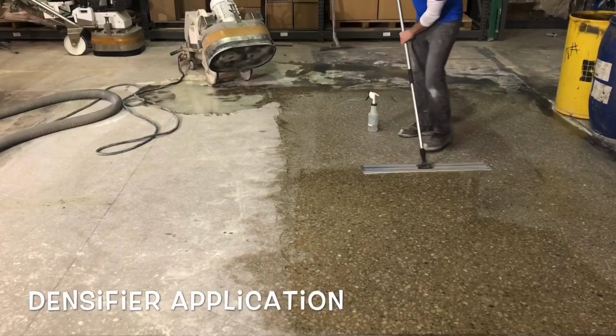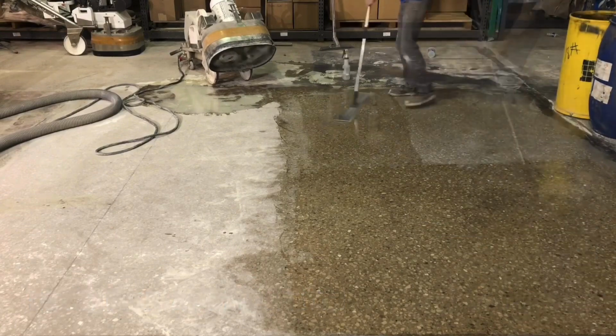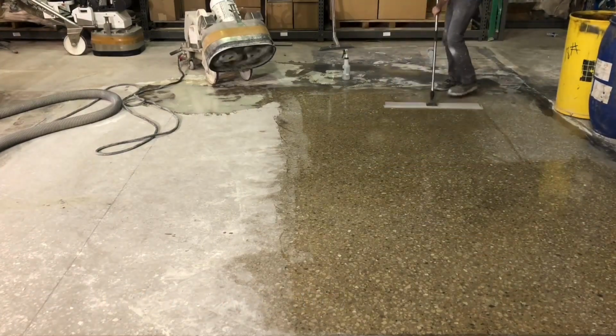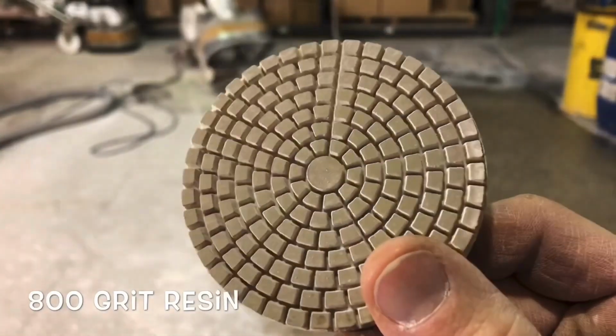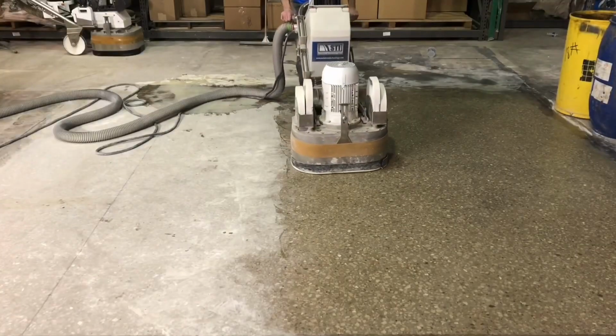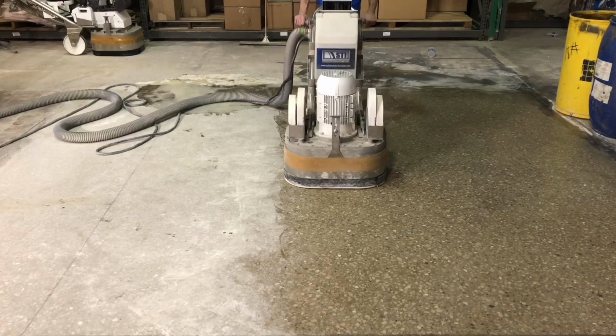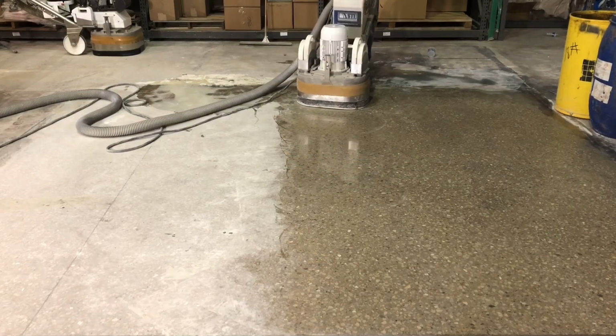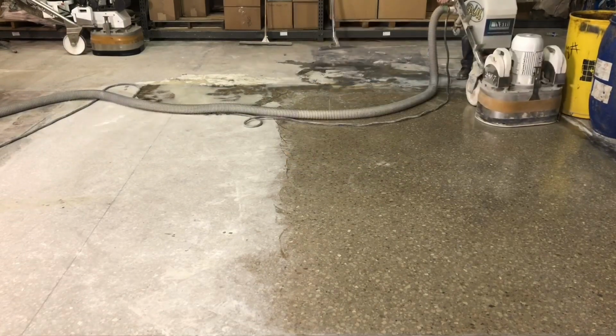With this process now complete, it was time to densify the floor. This particular densifier is a lithium-based densifier. It's specified to go on at 800 to 1,000 feet a gallon, so we were very careful to not over-apply the material. To finish the polishing process, an 800 grit resin pad was used to take out the scratches from the 400 rubber back and to then process the floor to its final result.